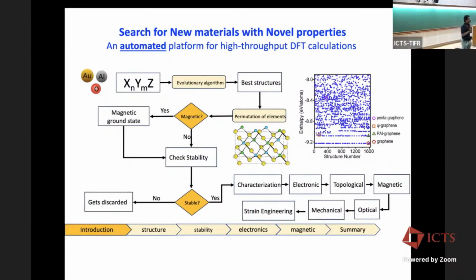The basic objective is to screen many materials, or to find new materials, and finally to come up with a few very important materials. We can start in different ways, but one of the ways that we do that is we take some chemical elements and mix them with some chemical composition, and then we do an evolutionary structure search algorithm to find the best possible structures, and then we see whether this is magnetic or not, and after that, yes or no, it doesn't matter. We check the stability of these systems by different means, and if it is stable, then we go for the characterization. If it is not stable, they are discarded.